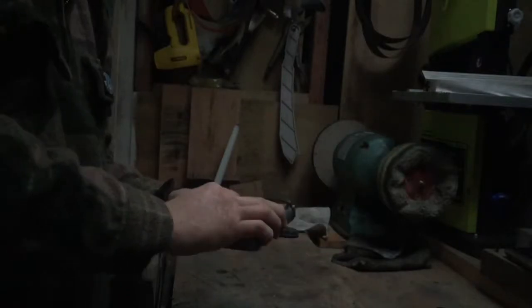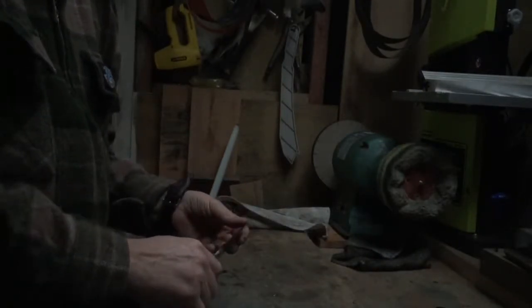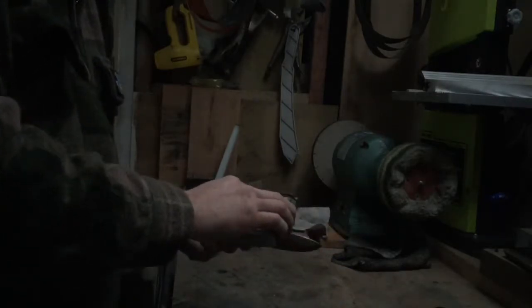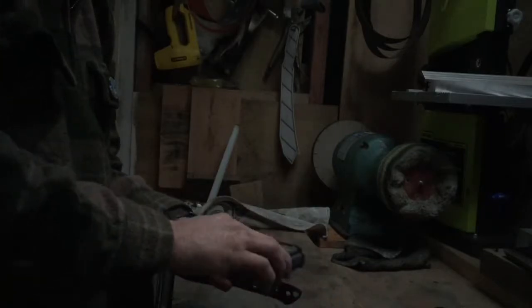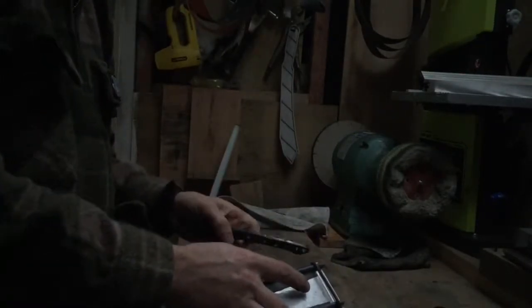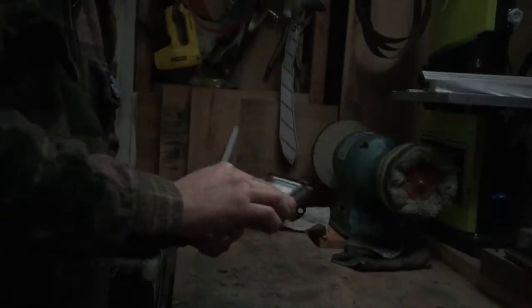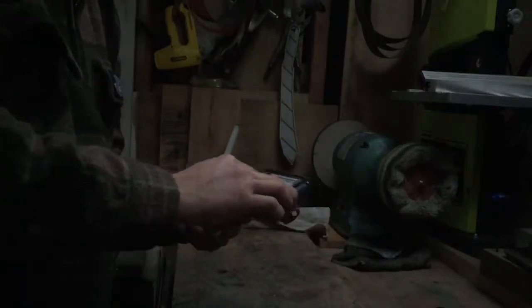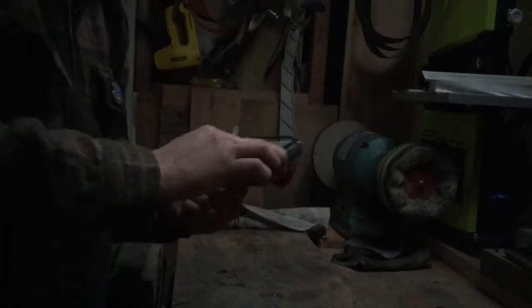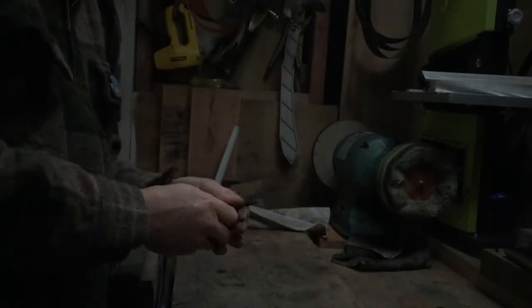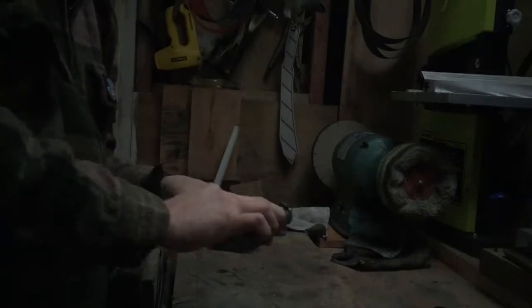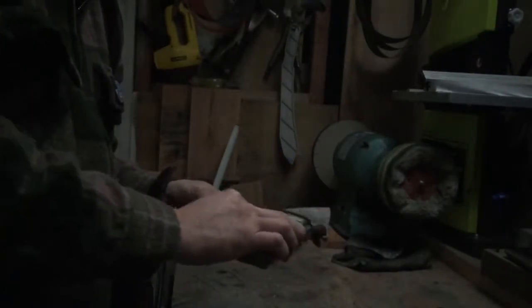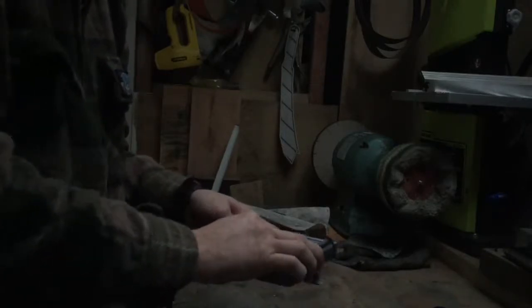Now O1 steel is what I use, and that gets heat treated first of all by heating it up to around 700 degrees centigrade, and then take the heat away and let it rest. This kind of gets it prepared for the heat, as it were. Then it gets heated again the second time, and this time it gets brought up to between 780 degrees and 800 degrees, roughly. It's the temperature at which the steel loses its magnetic properties. At that point it gets taken away from the heat and pretty much instantly shoved into a tub of slightly warmed oil.